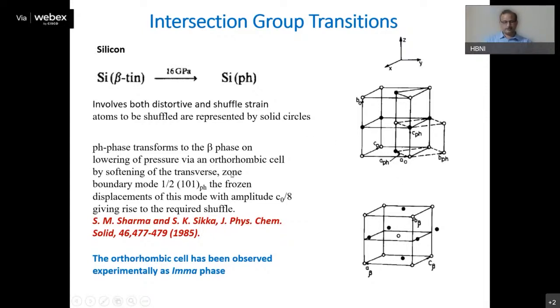And indeed, it has been shown in this paper by Dr. Sharma and Sikka that if you consider an intermediate orthorhombic cell, then in this case the zone boundary mode is the half 101 phonon mode. This actually freezes, and this corresponds to a displacement of about c0/8, and this gives rise to this phase transition. So there is an intermediate phase in this case also.